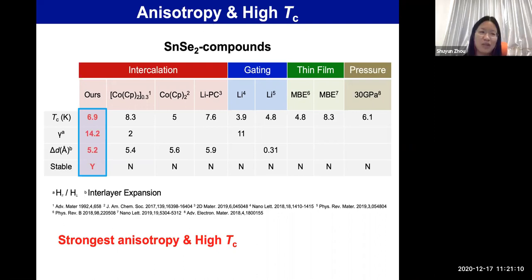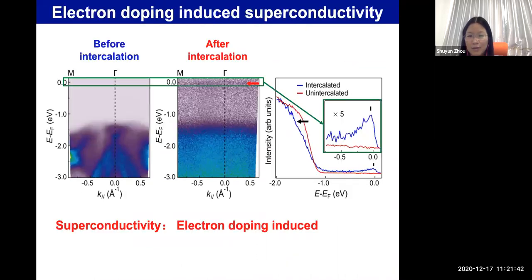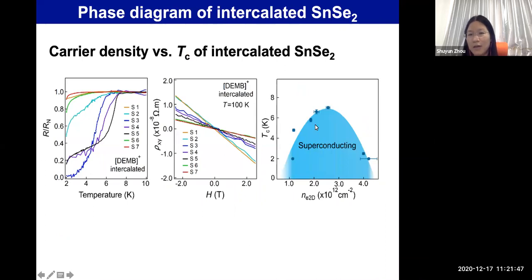Yeah, that's certainly something interesting to investigate. And actually, one puzzle that we have for the superconductivity in this molybdenum ditelluride is exactly this. We have measured quite many samples, and they may show a different carrier concentration, but the TC doesn't. We cannot find a correlation between TC and carrier concentration, like the one that we have here for this tin diselenide. So the physics for the superconductivity in these two materials is actually very different, and we are quite puzzled. You mentioned spin fluctuation as a possibility, and I'm not sure how that could be related here, but we are also trying to change the interlayer spacing of this molybdenum ditelluride.